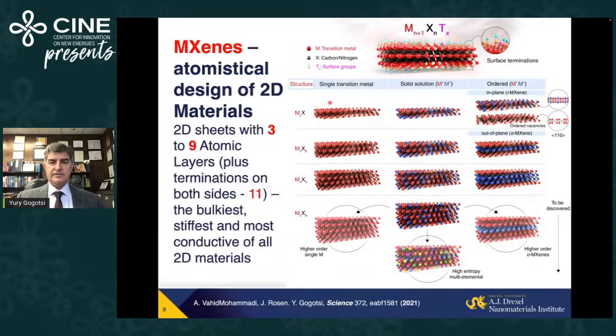Moreover, in this family of materials, we have already shown our ability to do engineering of materials at the atomistic scale. For example, we can have not only these structures with different numbers of layers of transition metal. We can also make atomic sandwiches out of out-of-plane ordered MXenes, where one metal is on the surface, for example, molybdenum, which will determine electrochemical, chemical, catalytic properties. But another layer in the middle, for example titanium, will determine conductivity, acting as an electron transport highway, because the conductivity of these materials, the majority of them are metallic, jumping ahead, is determined by the elements of transition metals.